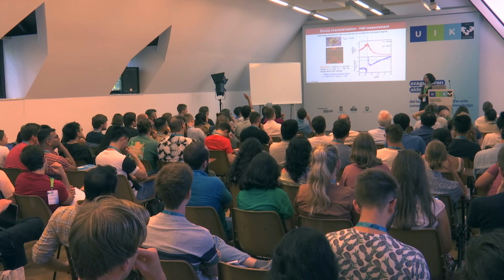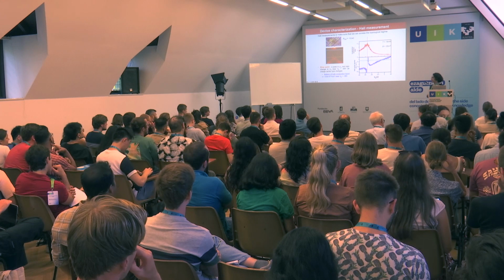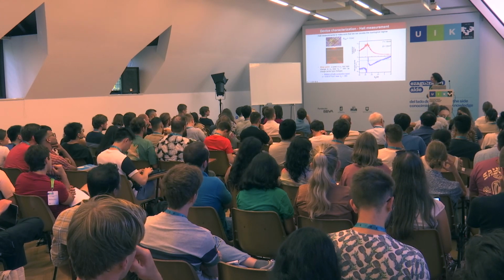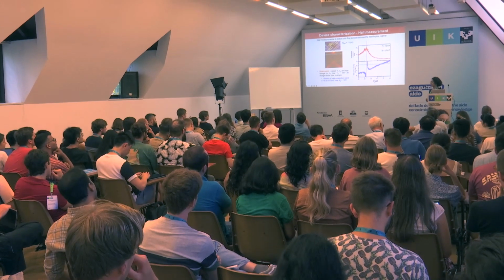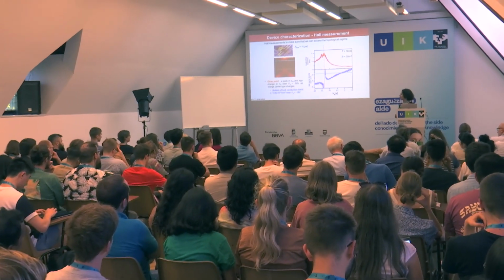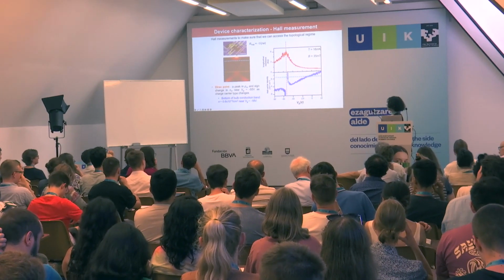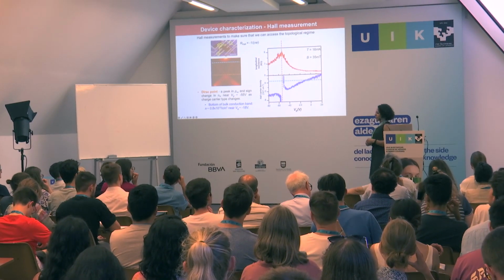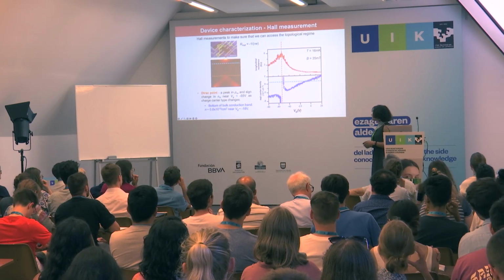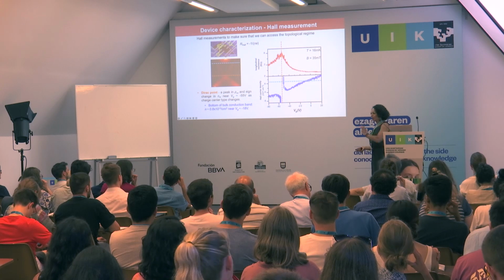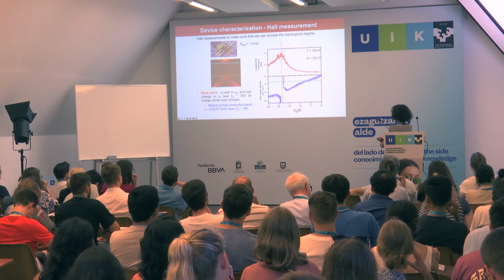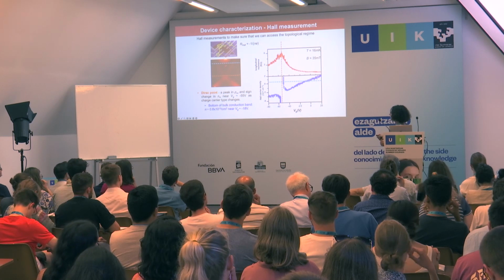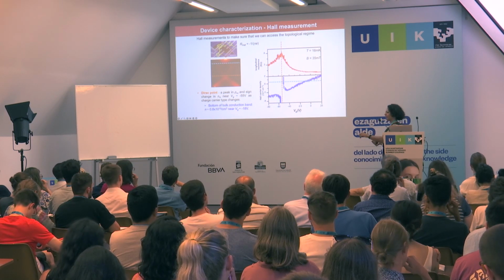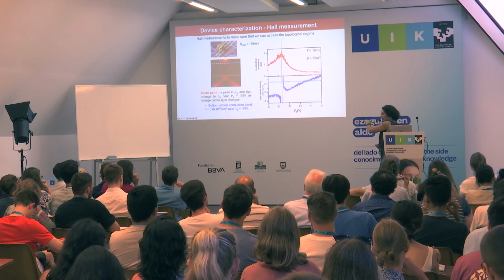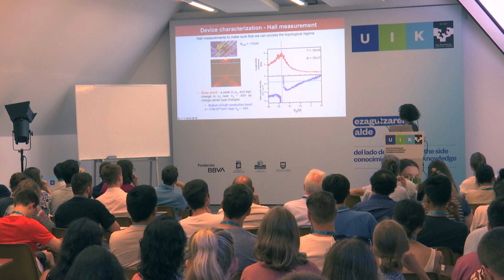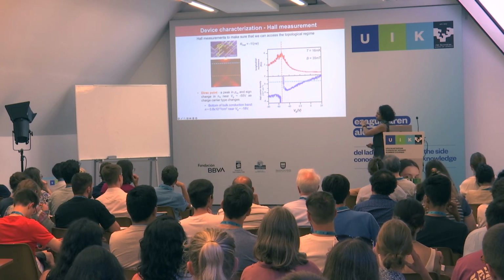With this chemical doping, have you ever observed that you shift the Dirac node up and down in energy compared to the surface? Because the Dirac node is not really fixed by anything. You could push it into the bulk, then. So we haven't done ARPES on a chemically doped system, so we don't know exactly where it is. When I say I know where the bottom of the bulk conduction band is, this is from comparing the ARPES of an undoped system to the ARPES of this system, and then assuming that the bottom of the bulk conduction band is around the same place. That would require actually doing ARPES on it.